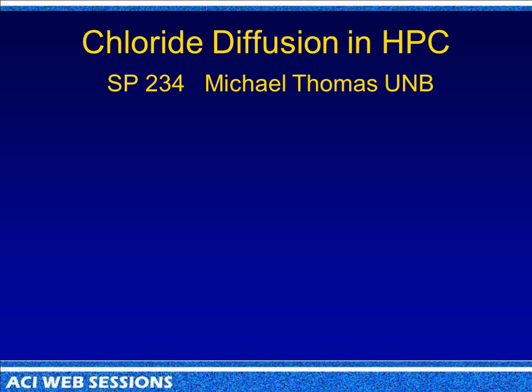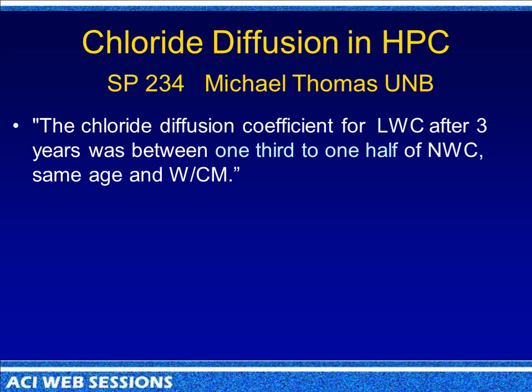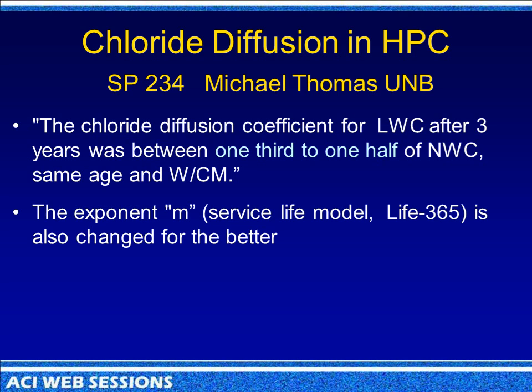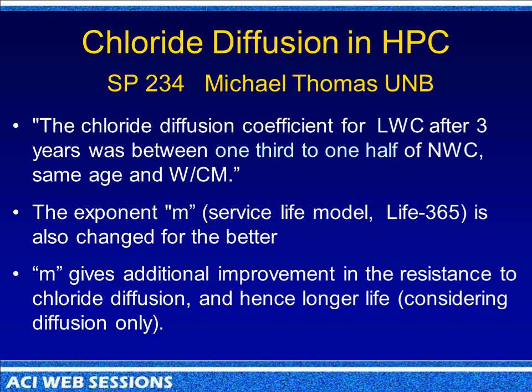Okay, chloride diffusion. Michael Thomas talked about this in the bottom line here at 3 years, 1/3 to 1/2 of the chloride diffusion coefficient by using lightweight concrete. And the M factor is also improved. The M factor is used in Life-365. And now this study was done just on the consideration of chloride diffusion only, but it definitely points in the direction of improving it.